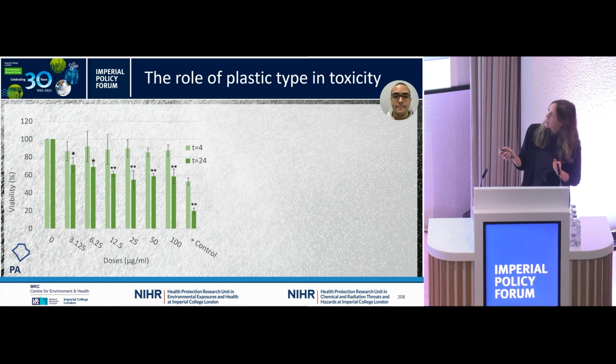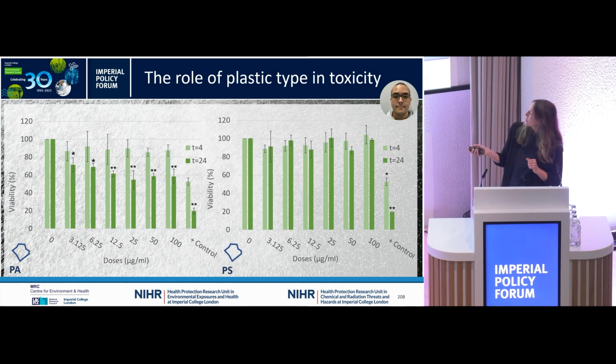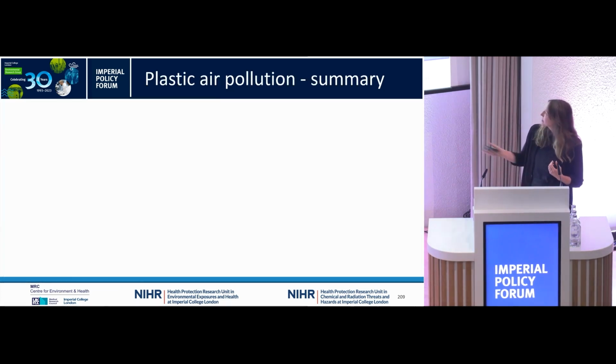So again, what you can see at 24 hours is significant drops in cell viability at quite a low concentration, whereas when we look at the polystyrene equivalent particles, we don't see any effect. At this stage, we can't say why or what it is about these. It's just very preliminary data to flag that looking at very simple microplastics might not be sufficient for capturing the diversity that we experience in the environment.